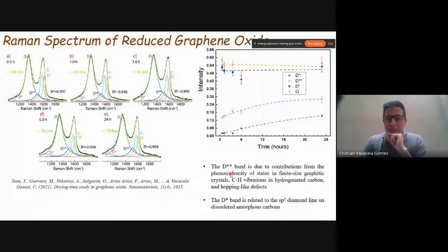The D star band is observed in amorphous carbons due to the presence of finite size graphite crystals, CH vibrations in hydrogenated carbons, or hopping defects. And also, the presence of the D star band is related to the sp3 diamond line in amorphous carbons. Of course, we are not working with amorphous carbons, but we have our graphene oxide sample. Depending on how the oxidation is done and how the reduction is done, we have these characteristics. So we can modulate, and maybe some of you can identify different applications for this type of system with these different effects.